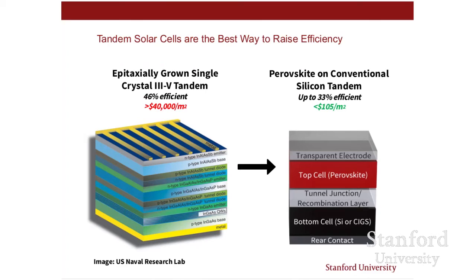And on the bottom, I think we could just use conventional semiconductors like silicon or copper indium gallium selenide, which both have the perfect 1.1 eV band gap. And then on the top, we need something that works even when it's not a single crystal, something that you would say is defect tolerant. And the perovskites have really emerged as an exciting candidate for that.